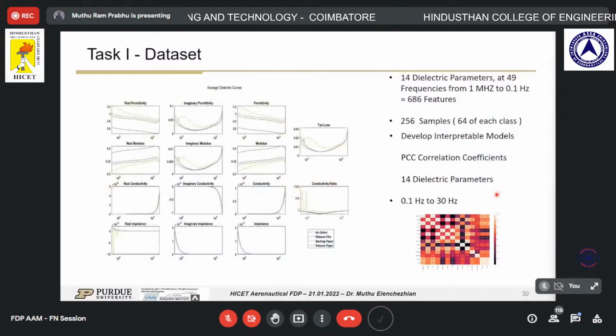Based on this, we collected a complete data set, and the data set was for a total of 256 samples. We had 4 different classes, so 64 data points for each class, and all of them have 14 dielectric properties. And these 14 dielectric properties were collected at different frequencies from 0.1 hertz to 1 megahertz, that is, during the entire dielectric spectrum. After that, we did a Pearson correlation analysis to analyze the correlation between dielectric parameters, and it was reduced down. Only the limited data set was used for the complete analysis.